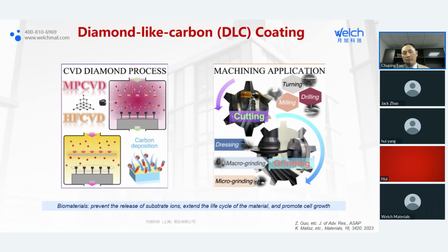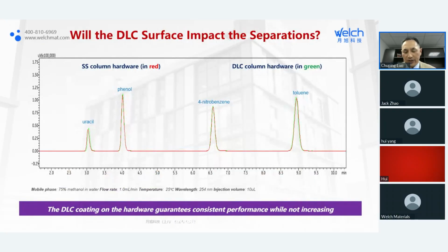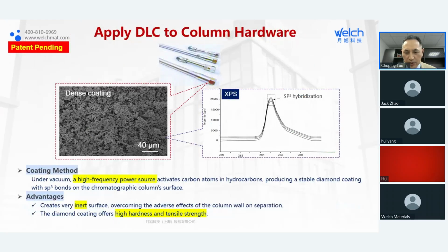So one worry comes out from that. Since we introduce the carbon to the surface, can that increase the hydrophobicity? That's something everyone will worry about. So we did one experiment here, a comparison between with or without coating. Typically people use this sample to QC the C18 columns. The red represents stainless steel hardware, the green represents the DLC hardware. The whole peaks overlap each other very well. That means we don't need to worry at all about the surface change.